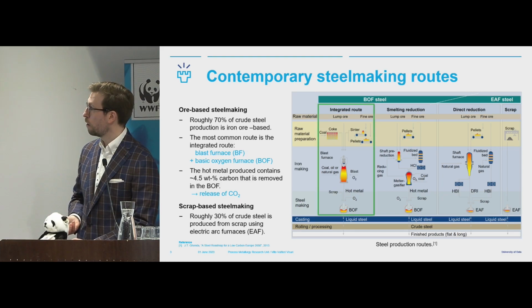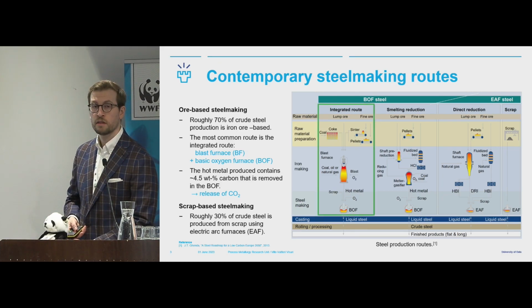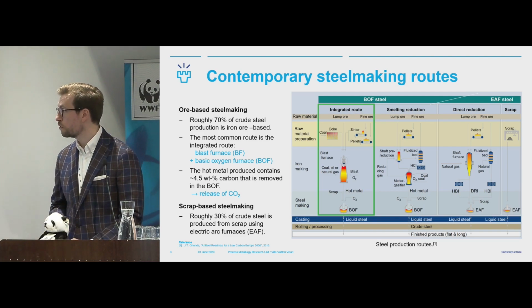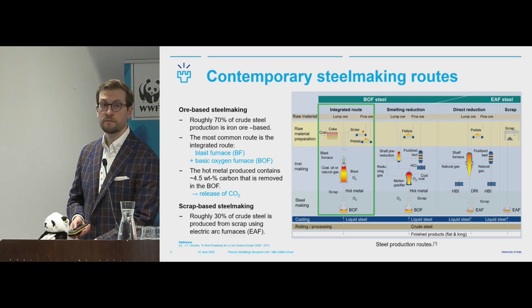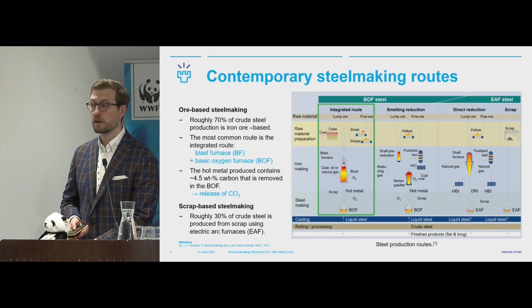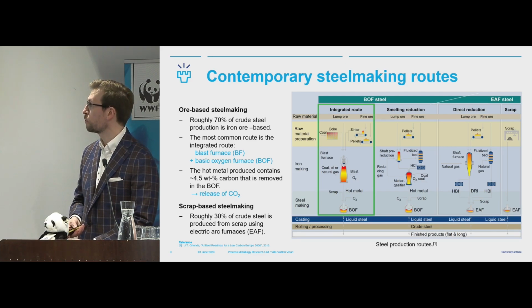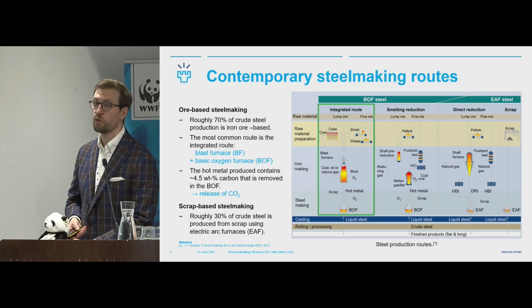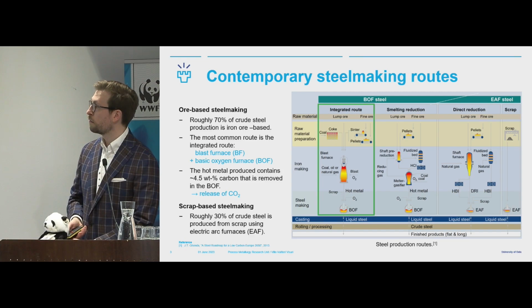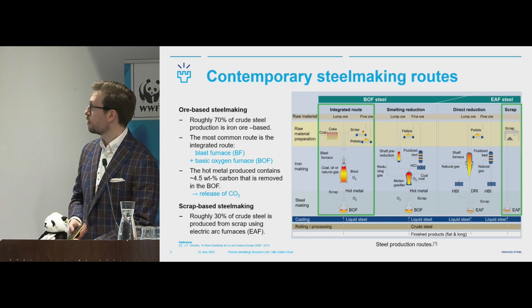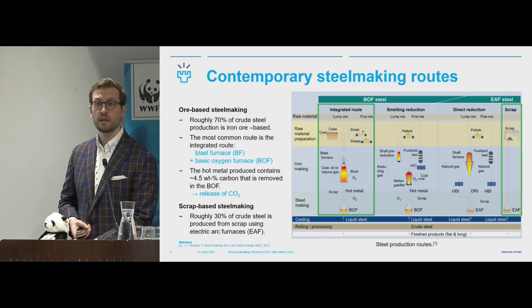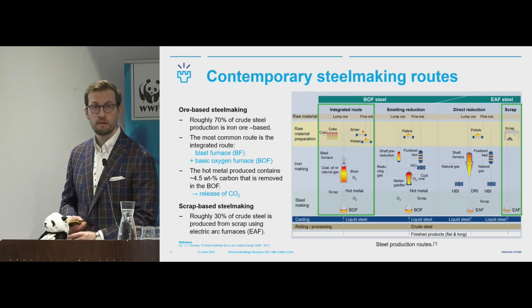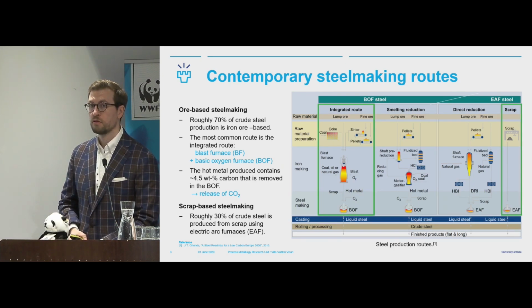The dominating process route for producing steel out of iron ore is this integrated route, where we produce the iron in the blast furnace using fossil reductants. We're talking about metallurgical coke. Then we remove this carbon using oxygen blowing, the basic oxygen furnace, and thereby induce quite a lot of CO2 emissions. Well, then the other major route is based entirely on scrap. We use electric arc furnaces to melt scrap and other materials to produce steel.